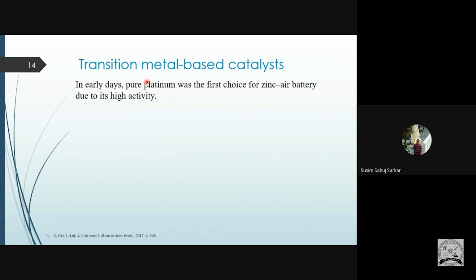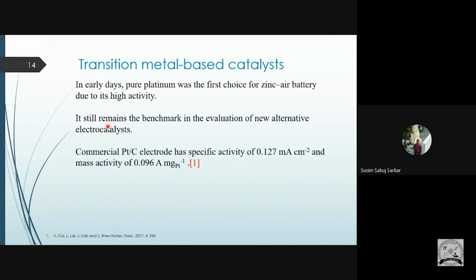So in the early days, pure platinum was the first choice for the zinc-air battery due to its high activity, because platinum has a very high oxygen absorption capacity. That means it can absorb oxygen easily, and it shows very high activity. It still remains the benchmark for the evaluation of new alternative electrocatalysts. So when a new electrocatalyst is introduced, we use a platinum carbon electrode as a benchmark, to see whether it is outperforming it, or how close it can get to this platinum carbon electrode. Commercially, the platinum carbon electrode has a specific activity of 0.127 milliamps per centimeter square, and the mass activity is 0.096 milligram inverse.